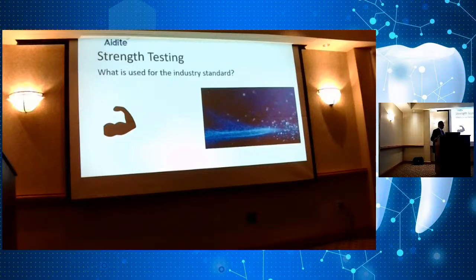Yeah, I'm thinking about starting to try and make veneers out of zirconia. I'm starting to like those results better than the Emax, going through the process of waxing and this and that. If you do a beautiful zirconia veneer, in my opinion, it has higher strength than your normal feldspathic or lithium disilicate. The only worry I have about veneers is them coming off, not breaking.